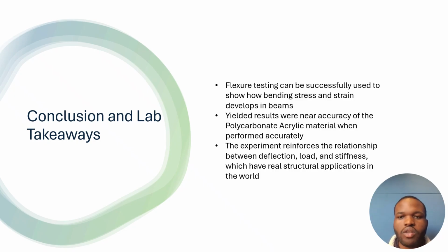And a result of that is that our Young's modulus that we have is consistent with the actual Young's modulus of the material. So that showed that our setup and data collection was accurate. The experiment reinforces the link between deflection, load, and stiffness, which is seen across the real world. So it showed that those three things are aligned together. And you can see this in the real world, like with bridges, aircraft structures, and more, right? Because all of these things have to be taken into account, in terms of what it's going to be used for.